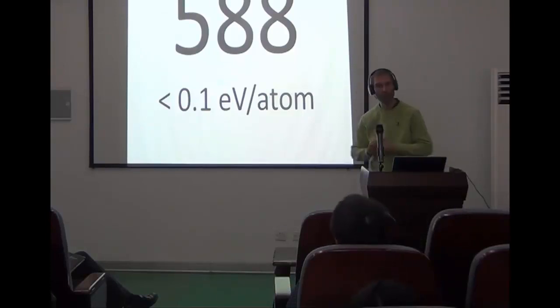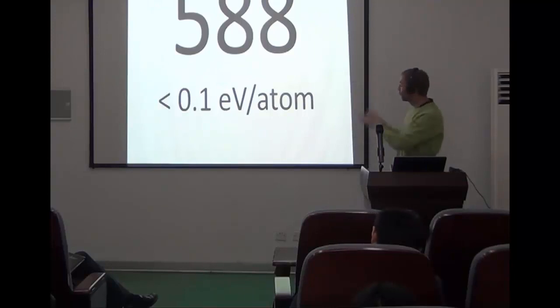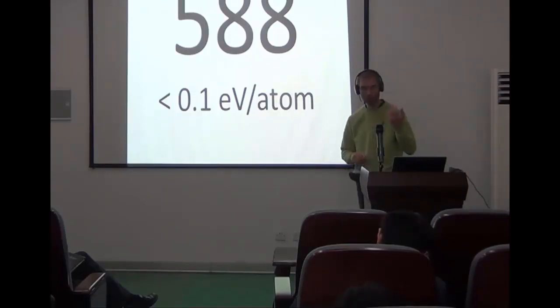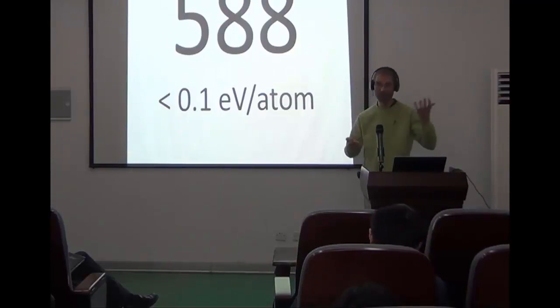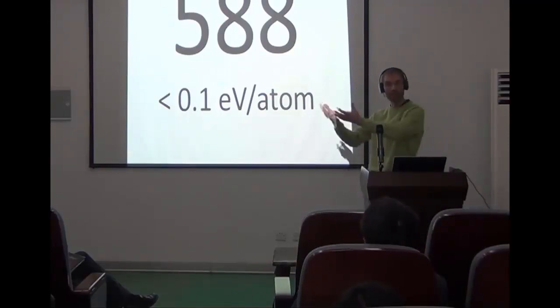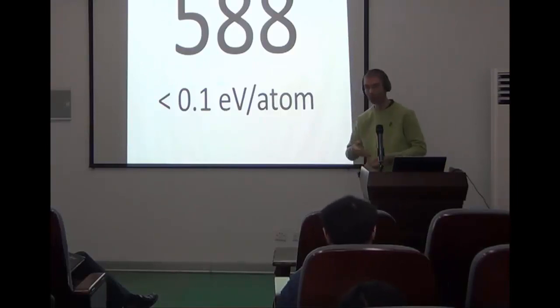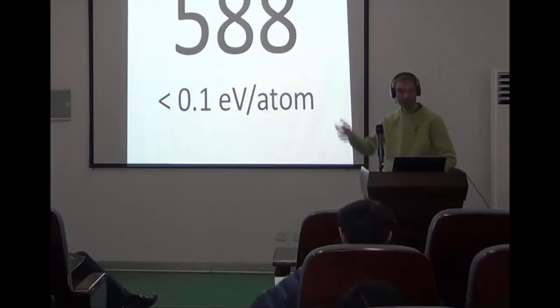So that is the information we give to the experimental people. This set of 6 or 80 crystals, that's a good set to start searching. If you try a synthesis of these materials in the lab, chances are very high that you will be successful. And remember, I told you finding one of these new materials is the reason to publish a paper. Here they have the chance to find immediately not one, but many of them. So this can really speed up the discovery rate. So we go from 6 known crystals in that search space to probably of the order of magnitude of 100.